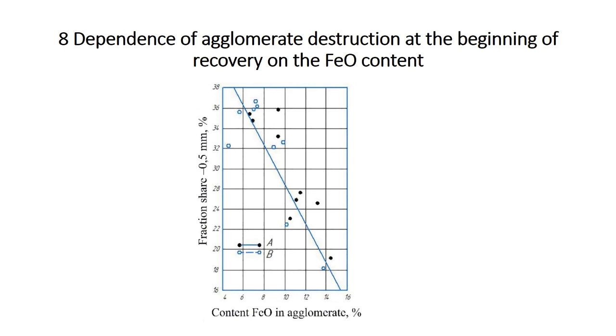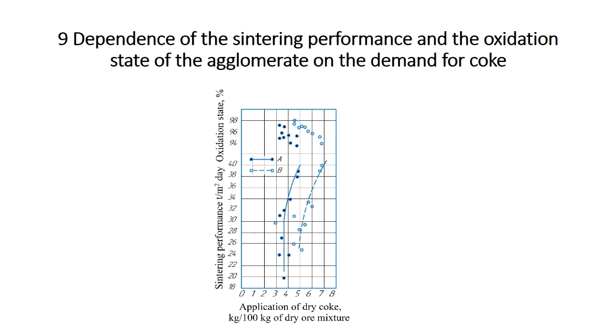Figure 9 clearly shows the difference in the demand for coke when using hematite and magnetite ores. To achieve the same productivity, this requirement for both ores differs by 1.5 to 2 kg of coke per 100 kg of ore mixture. The demand for coke also determines the FeO content or the oxidation state of the agglomerate. With the same fuel consumption, the oxidation state of sinter from hematite ore B is 2 to 3% higher than sinter from magnetite ore A.